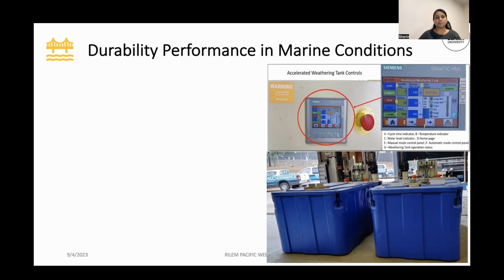weathering tank chambers. For this, specimens are immersed in artificial seawater for 12 months, and the type of specimens used include the beams as shown in the pictures earlier, as well as the cylinder specimens. The beams were reinforced with basalt FRP, and we also had beams which are reinforced with steel bars to compare the performance of both under marine environments.